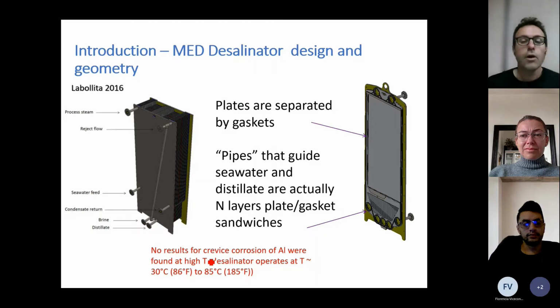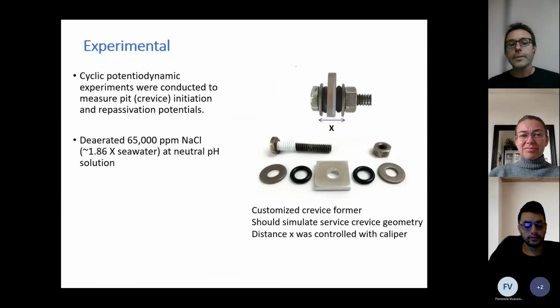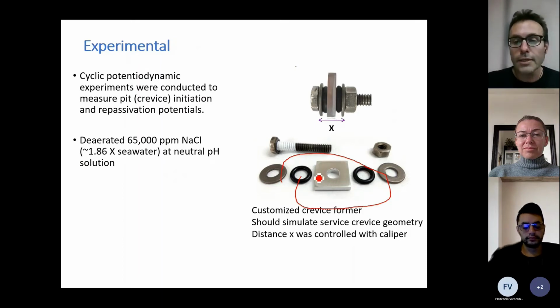And when you have an unknown, all of us who did a PhD, we know we have an opportunity. So the focus of this research project was tailored to find what was the effect of those gaskets that form crevices on aluminum corrosion. So to do that, we did some cyclic potentiodynamic experiments, and our sample was made specially so that it mimics the service condition. We use O-rings to simulate the gaskets. Those O-rings were fixed to the aluminum plate. The aluminum is here, and here you have the crevice.